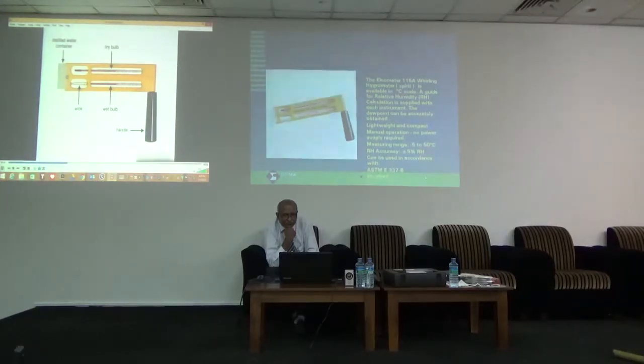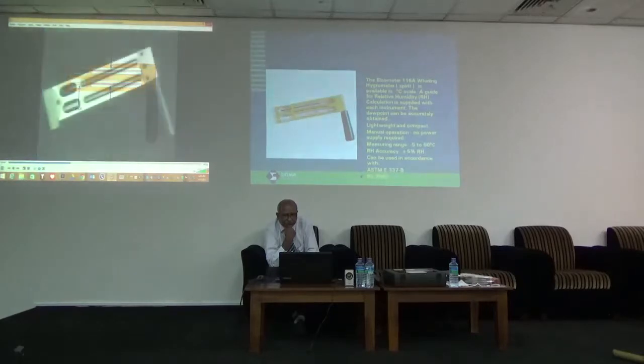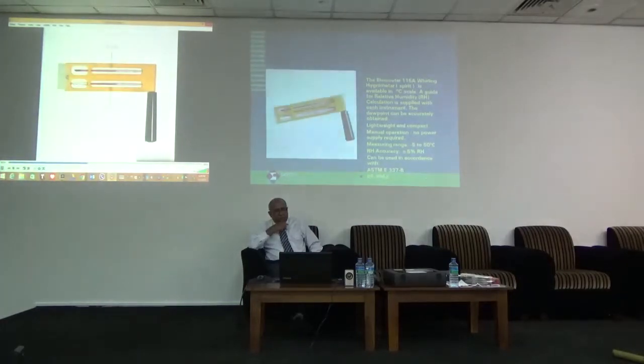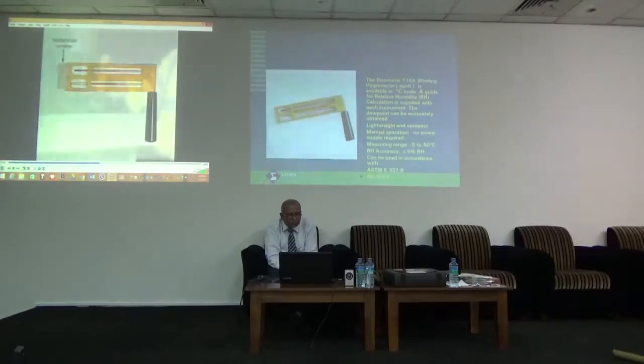The assessment for relative humidity at dew point is usually conducted by the supervisor or quality control personnel. The process is quite simple and can usually be performed by trained coating applicators. Ensure you check the whirling hygrometer before it is used for wear, tear or damage. Also check that the bulbs are not broken, the wick is clean, and the instrument has distilled water in the holder.